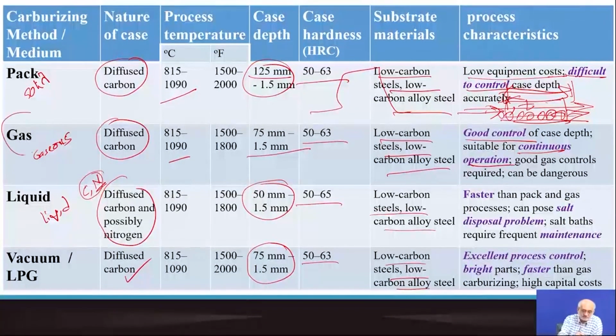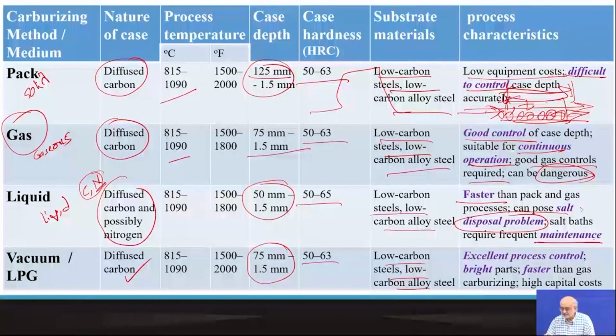You can also do very precise gas control, but it can lead to certain danger if the hydrogen released is not removed in time, or some other exothermic gas mixture combination can evolve. Liquid carburizing is faster and also more precise, but the biggest danger comes during the operation. You have to prevent any escape of cyanide gas or cyanamide gas or spillover from the tank, and also it's a highly corrosive salt, so maintenance of the tank becomes another major problem. In fact, in most cases this is no longer practiced, practically banned in some cases, but it actually offers a very nice, interesting metallurgical process.